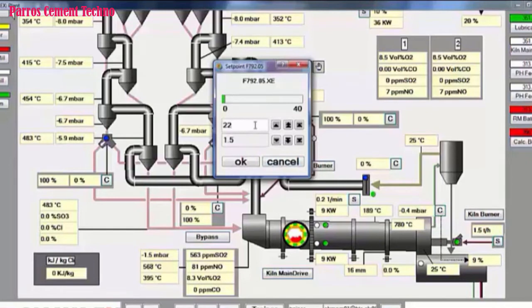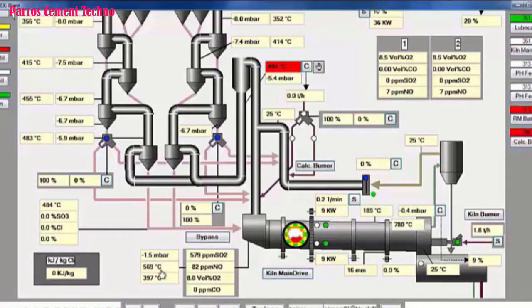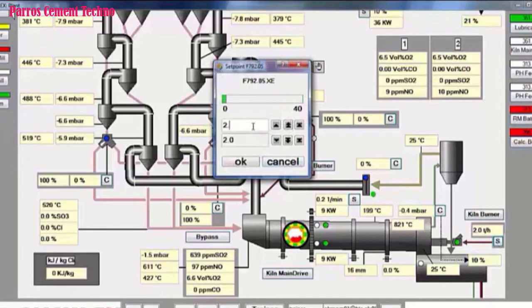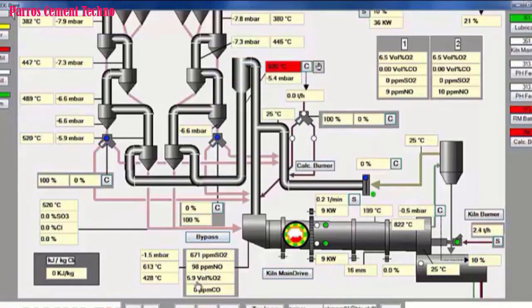We will increase the use of coal fuel again, to 2 tons per hour. Then we observe the temperature in the kiln inlet and sintering zone slowly rises, and O2 is still sufficient. In this 8th hour we use 2 tons of coal per hour and 2,000 liters of oil per hour. Meanwhile, the temperature in the sintering zone is 820 degrees Celsius and the temperature in the kiln inlet is 610 degrees Celsius. We increase another half a ton of coal consumption in the main burner, to 2.5 tons per hour.